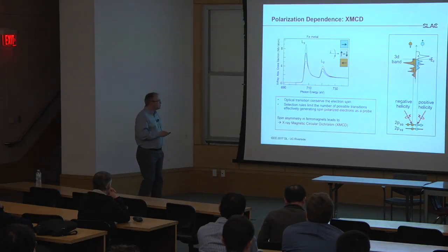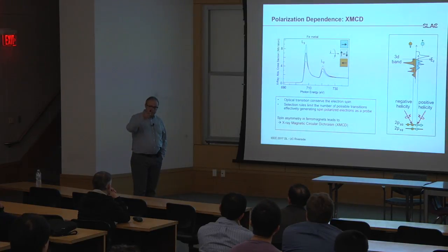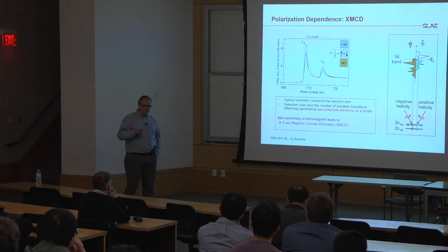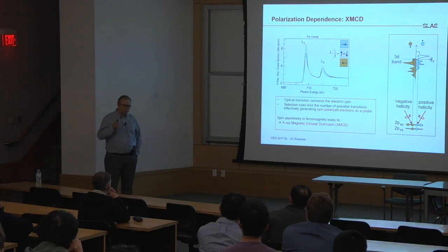The reason is that to see something, you actually need the spin-orbit coupling down here as well, which in oxygen you don't have, because you go from a K edge, from 1s to 2p. So you don't have this spin-orbit coupling. That means you cannot actually see the spin. You're not sensitive to the magnetic moment of the sample, to the spin. You're only sensitive to the orbital moment. The selection rules still apply because the selection rules are given by the orbital moment.